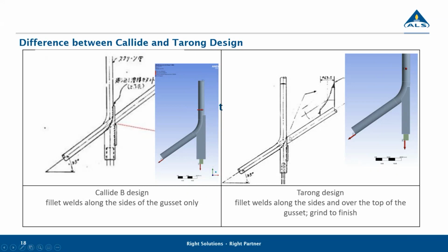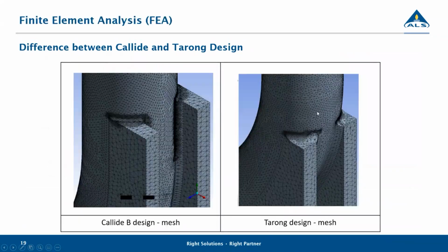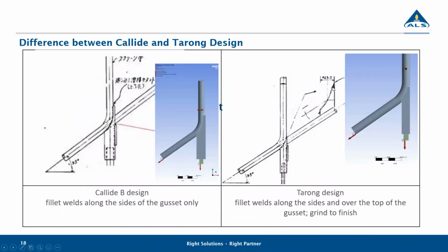Tarong design, slightly different, which is strange. It's an older boiler, so you would have expected that the design would be improved from Tarong to Callide, but in Tarong's case, the bracket stopped almost on the bend, and you can see here at the top of the bracket they actually filled in that little abrupt change to blend that weld in. And I've been on site looking at that specific geometry, and it looks pretty blended in there. You almost can't see a notch. So that's a big difference in the finish.